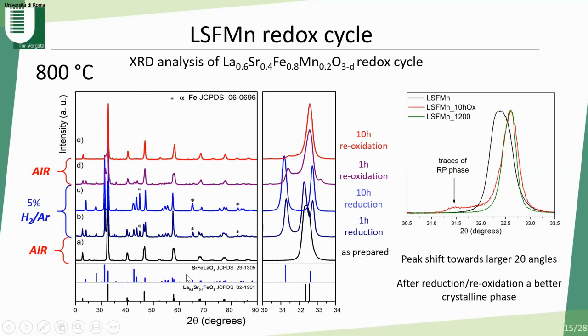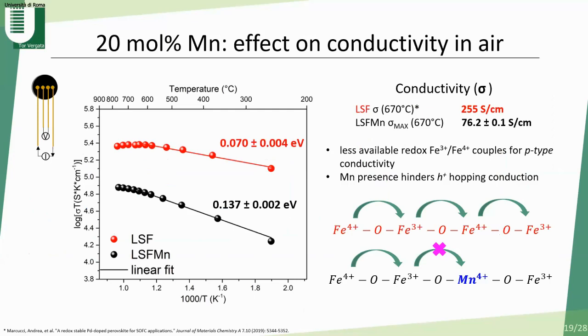So what is the role of this manganese oxide? It is an intermediate compound during the perovskite to Ruddlesden-Popper transformation that promotes the formation of a single Ruddlesden-Popper phase, avoiding the structural breakup, as in the case of LSF perovskite. So iron exsolves as metallic iron, while manganese is in the form of manganese oxide. After 10-hour reoxidation, we get the same phase with an even sharper peak at a higher angle. So it seems that maybe after reoxidation, we can get a better crystalline phase. So in this way, with this doping, we got a reversible crystal structure.